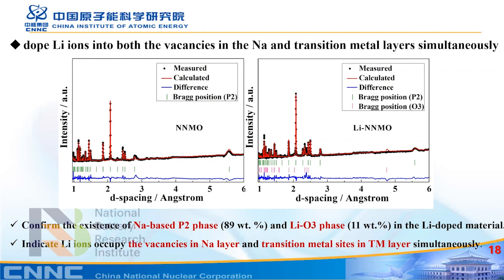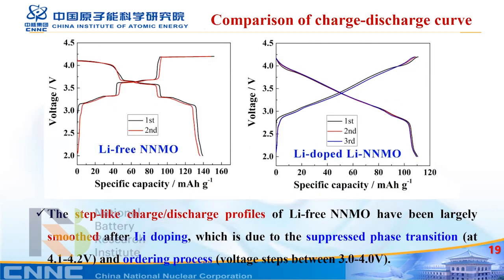Let's see the next page. According to the electrochemical performance test, we can find that the step-like charge-discharge profile of the Li-free material has been largely smoothed after lithium doping. This is due to the suppressed phase transition of the P2 phase to the O2 phase, that is at 4.1 to 4.2 volts, and the ordering process voltage step between 3.0 to 4.0 volts by inactive lithium ions.